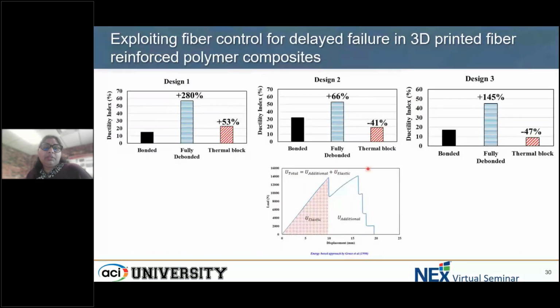We performed some ductility index measurements using the typical energy-based approaches by Grace. And designs 1, 2, and 3 performed very well in terms of fully debonded configurations for ductility. Bonded configurations obviously lack that sense of ductility, but the thermal block configuration of design 1 showed huge improvement on the bonded one.